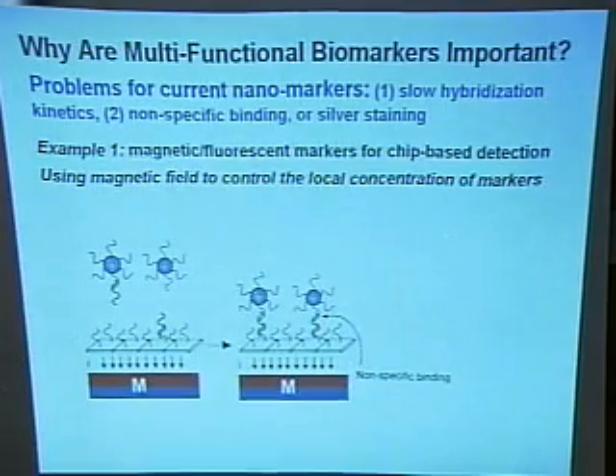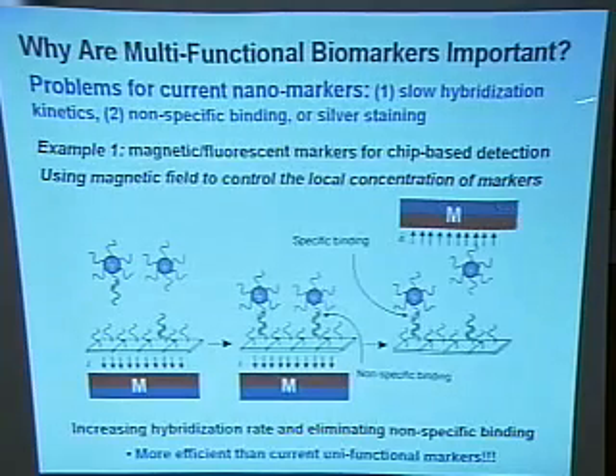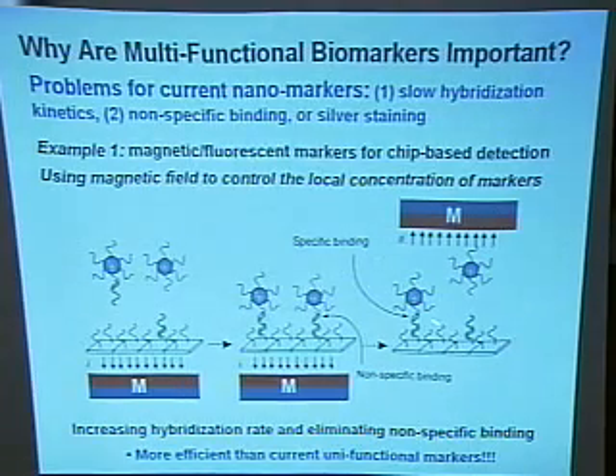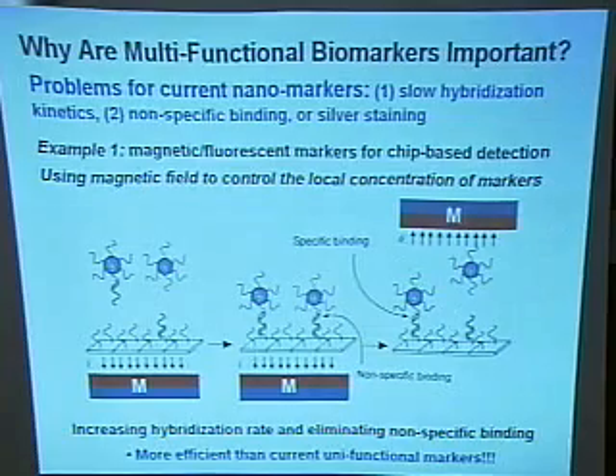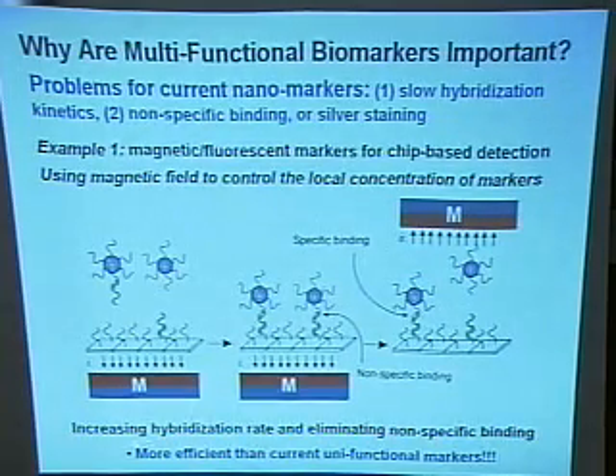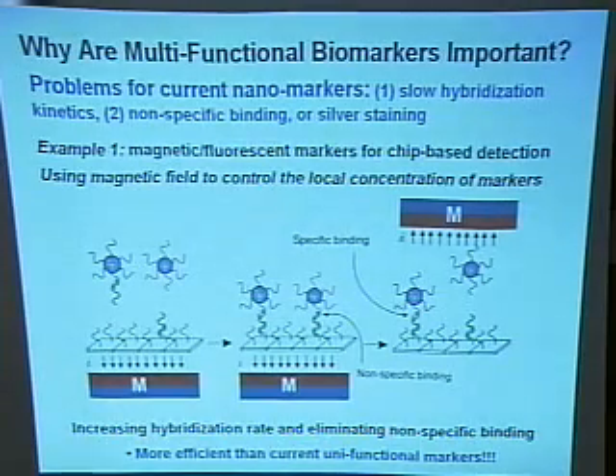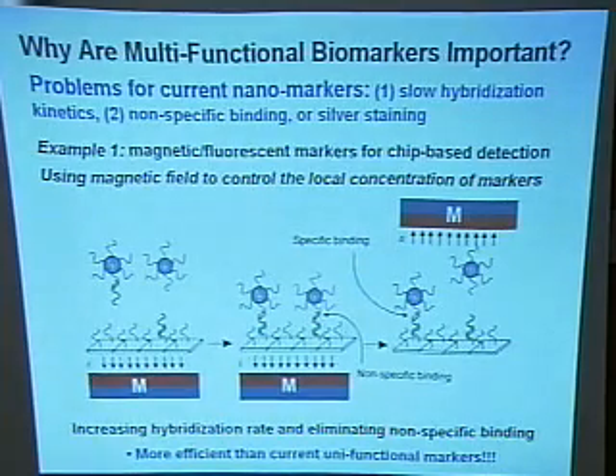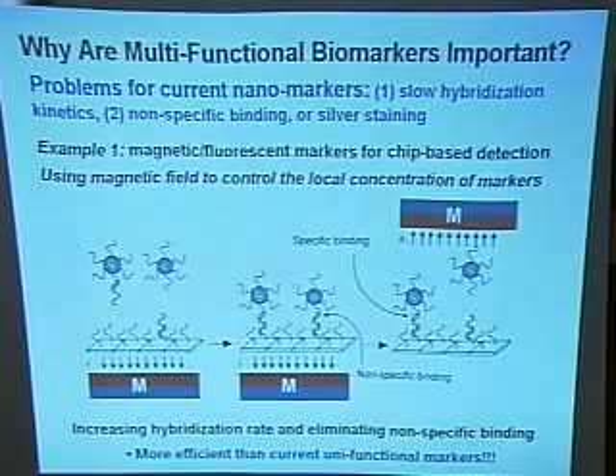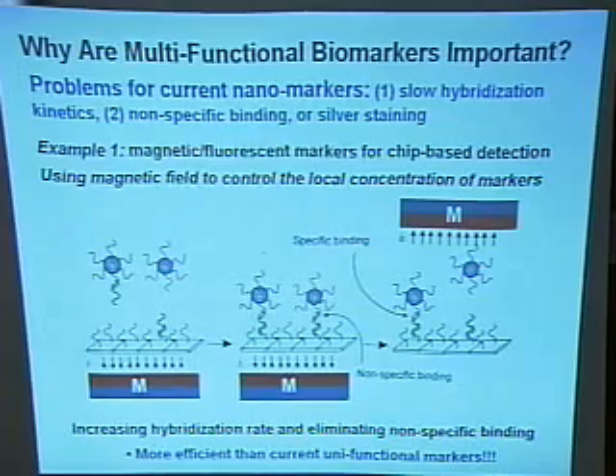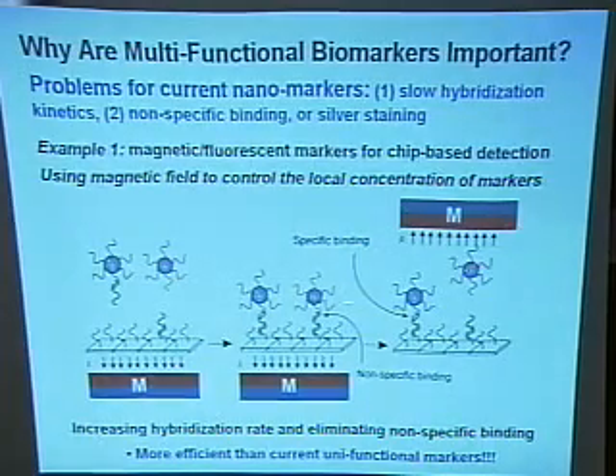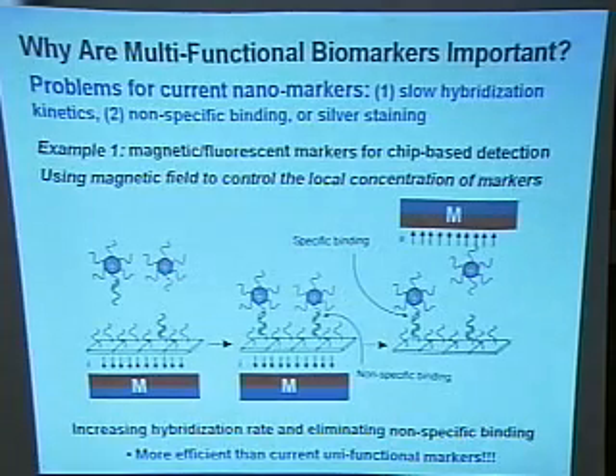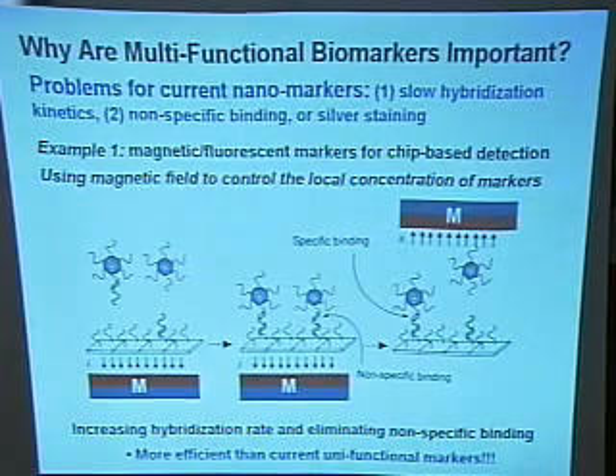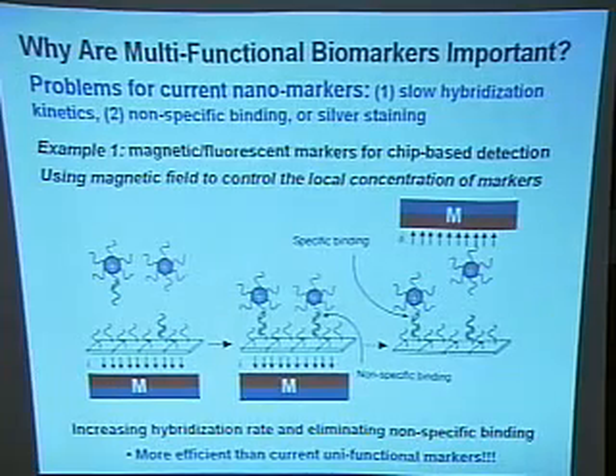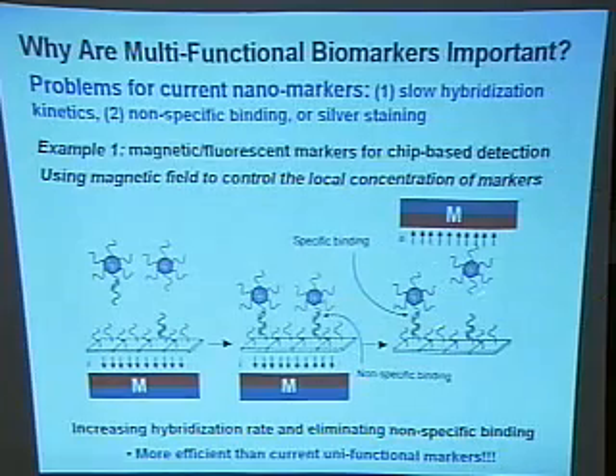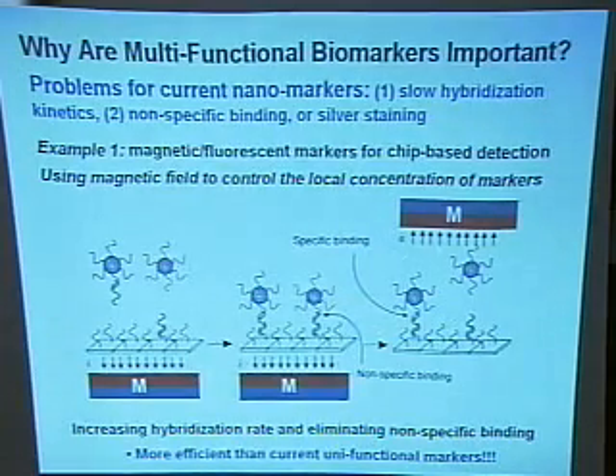Of course, you have the non-specific binding. Then the beautiful thing is you can apply another direction of magnetic field. You can selectively draw away the non-specific ones. So back and forth, many times, you can achieve increased hybridization rate and eliminate non-specific binding. Another beauty of this technique is you do not need to wash. Usually, people have to use a stringency wash to clean this non-specific binding. But if you use this magnetic field, you do not need a stringency wash. Usually the stringency wash has a huge kinetic problem that lowers your detection limit, because you take off some real complementary part from this detection.